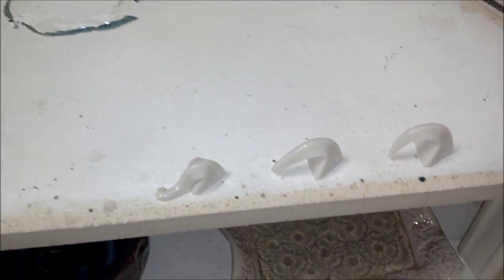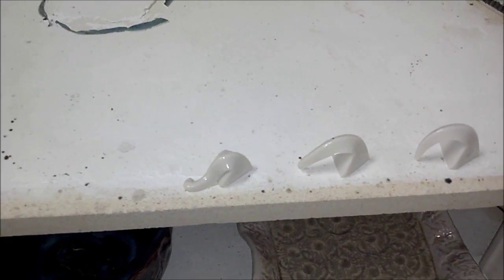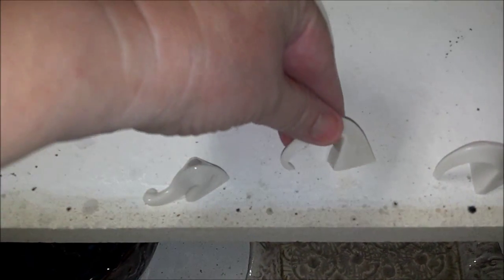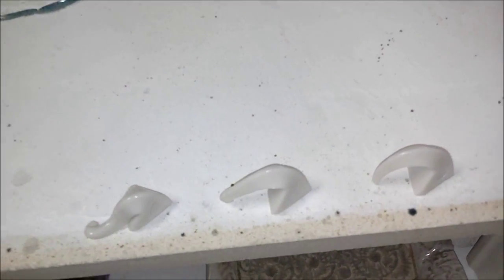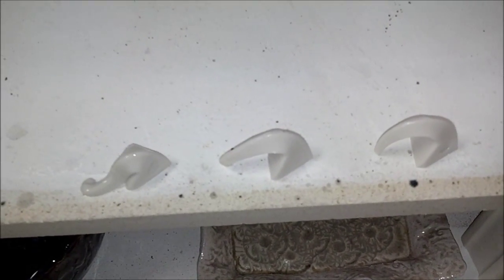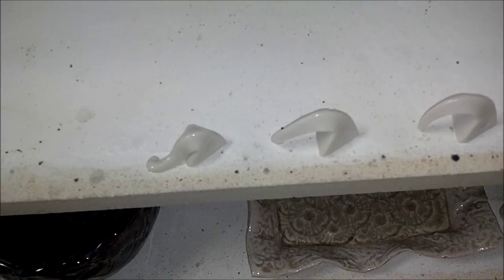I also wanted you to notice that Cone 5 is definitely melted on the shelf. Cone 6 appears to be okay — it's almost almost too much. And then that's the 7. I think what happened was that 15-minute hold really made it cook in there. So I'm very happy with this — it turned out pretty good. As far as testing the kiln, I think it's working properly.